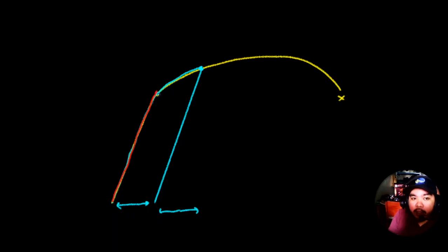Pero, pagdating dito, hindi na siya mag-yield at this point, no? Because your metal has been compressed and it has undergone plastic deformation. Therefore, nagkaroon na siya ng strain hardening. Okay? So, because it underwent strain hardening, mas mataas actually yung magiging yield strength niya. And in fact, when you continue this, the point wherein magko-continue siya to plastically deform will be the same point kung saan siya tumigil last time.